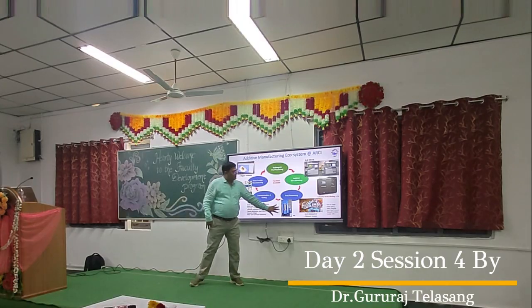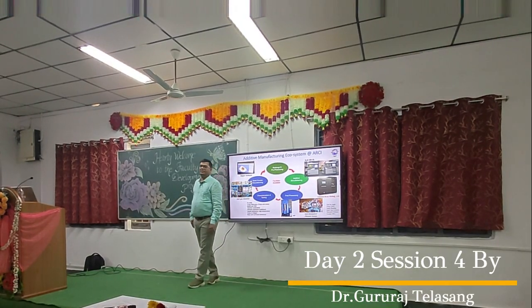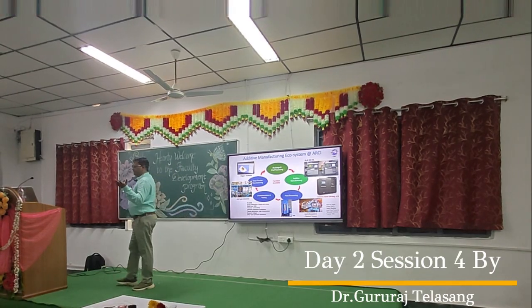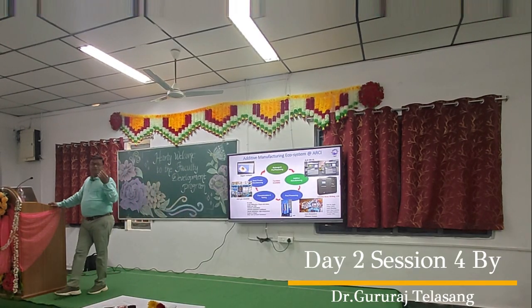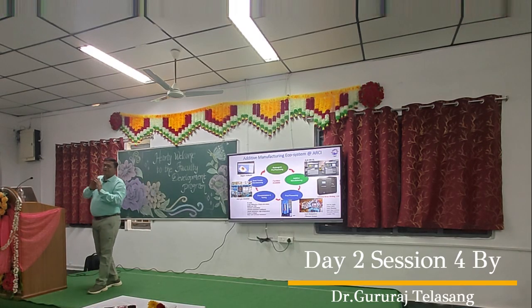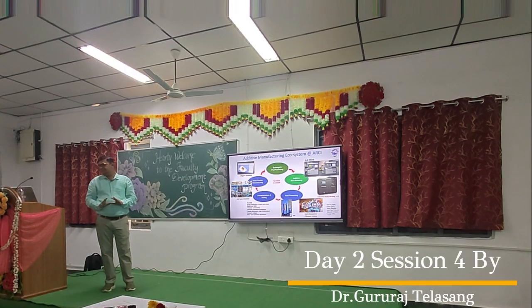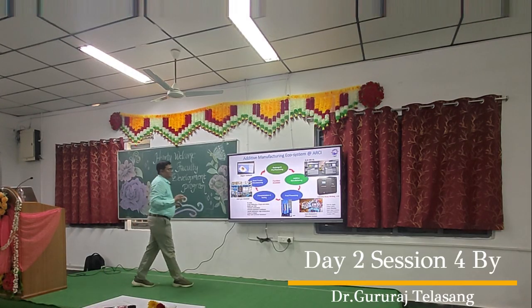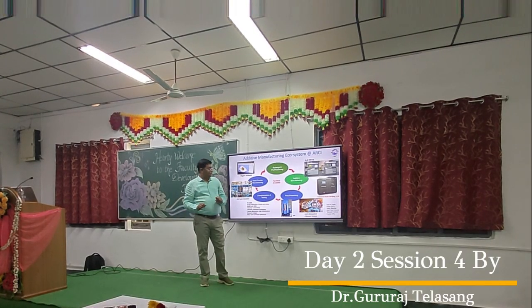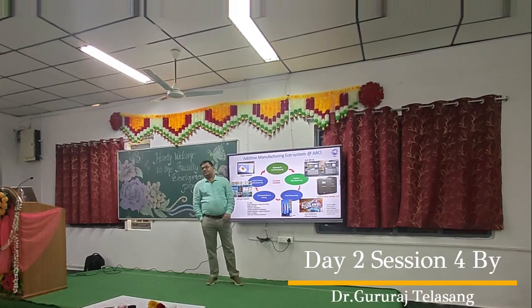These are the facilities for post processing, heat treatment and all. I told you it's a bundle of welds. If anybody knows about welding, they preheat before welding. They maintain some 200-300 degrees centigrade and then they weld. Sometimes they weld and then do heat treatment. Why? To bring back the normal microstructure from the anisotropy and stresses induced by welding. Same thing we have to do here. With a bundle of welds, we will have many residual stress issues, solidification issues, metallurgical microstructural segregation and phase segregation issues. All those things will be solved by post processing.